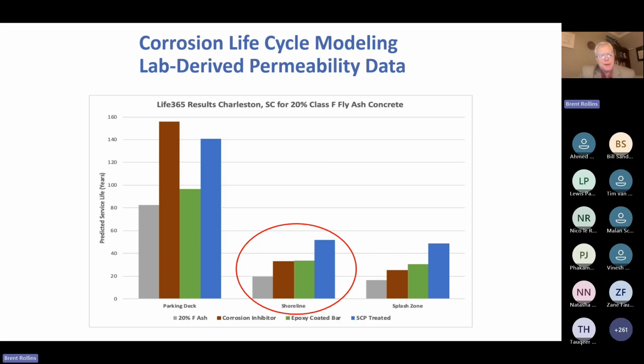But you can see that the colloidal silica treated concrete, compared to plain Portland cement concrete, had a 20-year life cycle at this particular coastal location. And this is the shoreline exposure. You can see that with colloidal silica, it's expected to last 50 years. So from 20 years to 50 years.